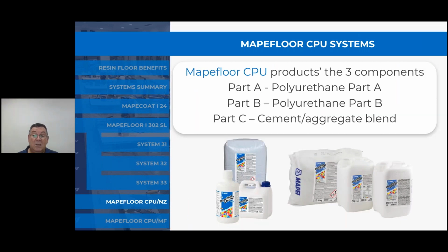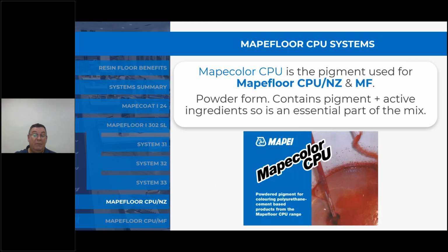So the CPU product consists of a 3-component, part A polyurethane, part B polyurethane, and a part C cement aggregate blend. But you must be careful that this can't be applied as a 3-component system. It must have the colour also added to it. The Mapecolor CPU is required in the Mapefloor CPU NZ and MF. It's a powder form pigment, but it also contains active ingredients that are essential part of the actual mix. So to not apply the pigment would not give you the complete system or the complete floor product as indicated on the data sheet.